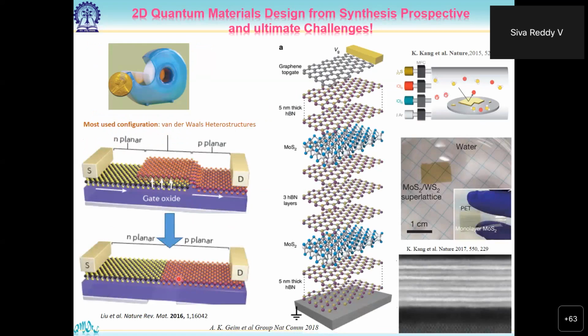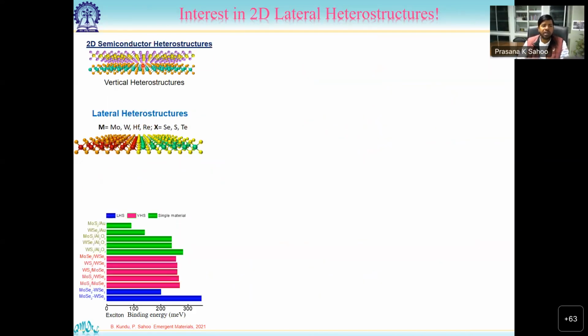So now we'll talk about lateral heterostructures. This is called in-plane heterostructure or lateral heterostructure. In 2D materials, you can make either vertical or lateral heterostructures. The exciton binding energy of these heterostructures is sometimes comparable to the vertical. But you can truly realize a 1D geometry, right? A one-dimensional channel when we are combining two lateral interfaces, where it is predicted that exciton binding energy can be even stronger because of the strong coupling between different regions. So binding energy can be stronger even than in vertical or pure materials.